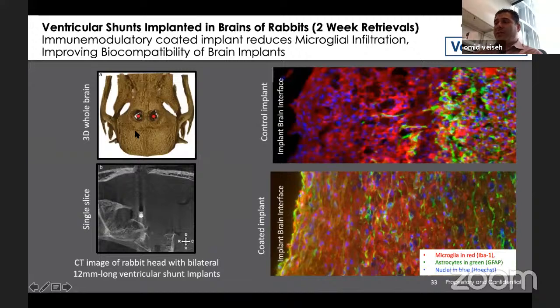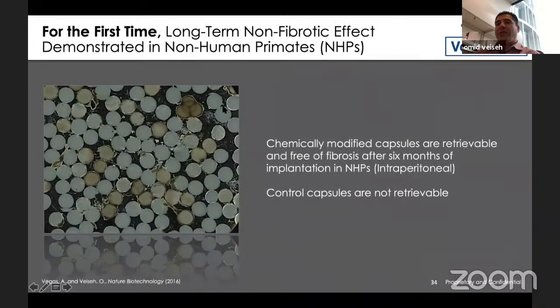And of course, there's a component of this device that goes into the brain, which is a different implant site than the peritoneal, where we've been testing these so far. And even in the brain, where the immune cells that are responding are microglia and astrocytes, we see a dramatic reduction of the inflammation when the coating is applied to it. So regardless of implant site, this actually works very well. We're now working with Medtronic to test this in an efficacy model where you can create hydrocephalus and show that this does lead to better outcomes.